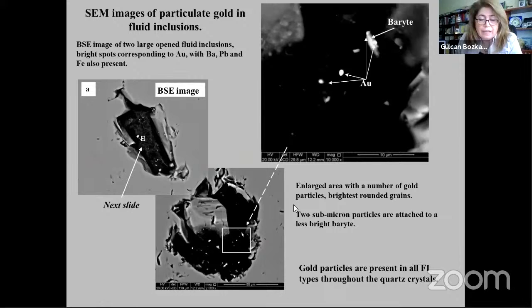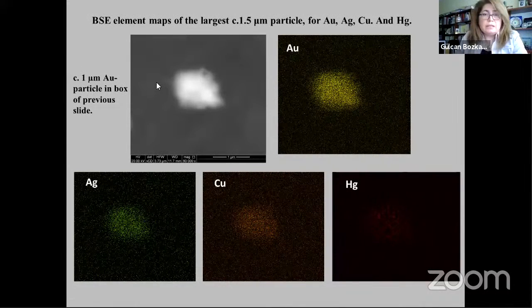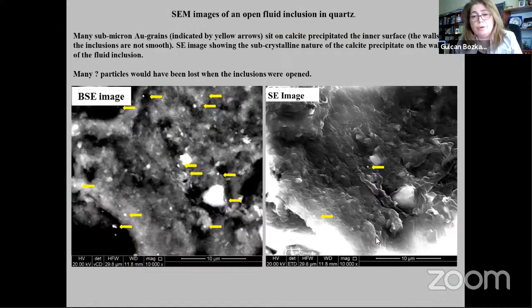The majority of the contents will have been lost, but we can still see some gold particles attached to the inclusion wall. The particles are always rounded, as you can see here, and the brightest spots due to their high atomic number. Here is the backscattered element map of one of the largest particles, about 1 micrometer. In the element maps, we can see gold, silver, copper, and mercury are present. So these are effectively particles of a gold alloy.